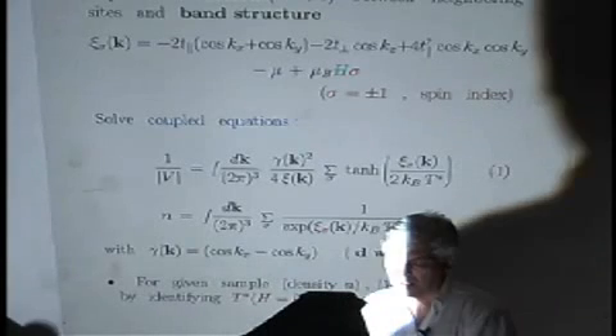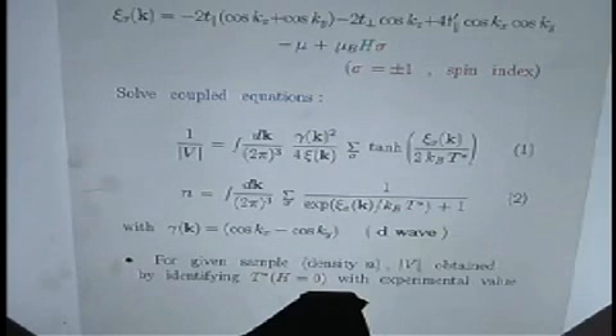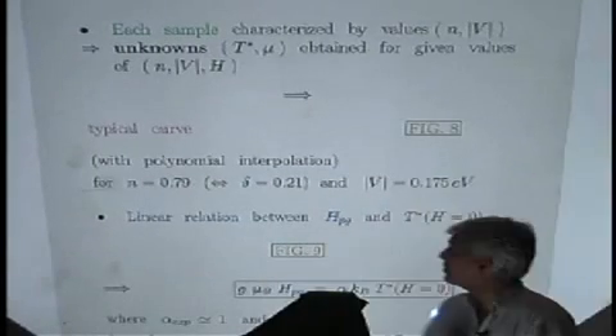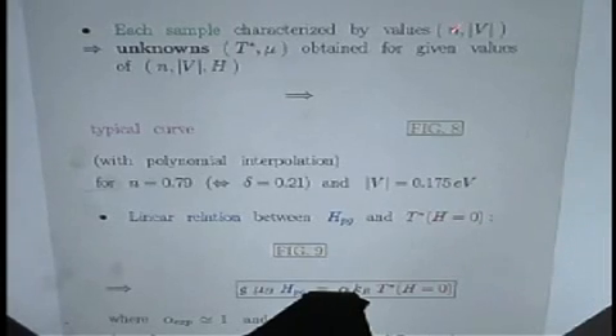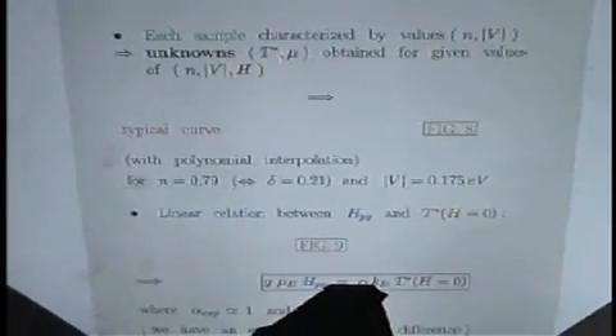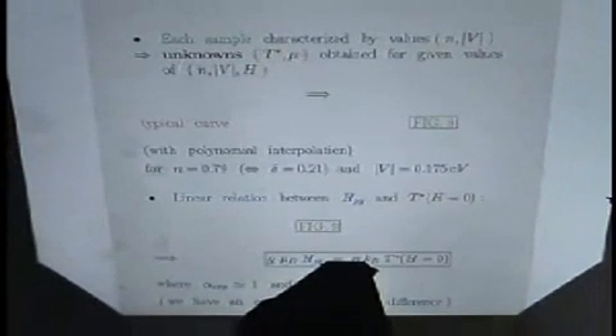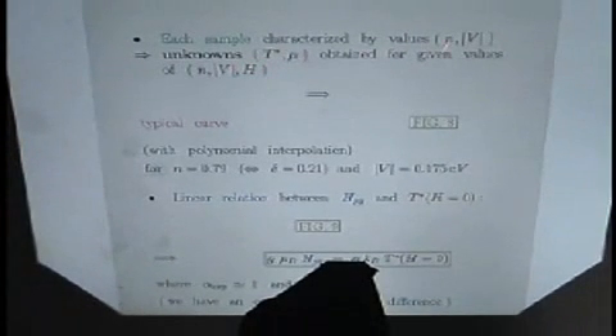Now, we solve, of course, we don't know what this number is, so we take it from an experiment by identifying the critical temperature, this T-star temperature at zero field, with the experimental value. But this is the only information that we take from experiment. Then we solve the two equations for the unknown T-star and the chemical potential for a given sample, so for a given value of the density and of this coupling, for several values of the field.